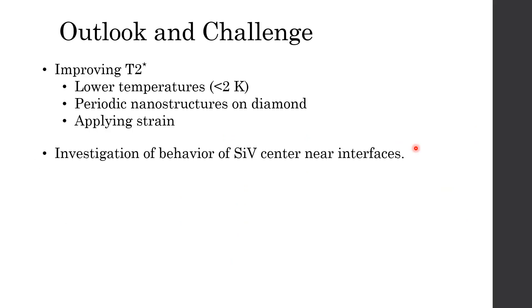Since the coherence time T2 star is limited by orbital relaxation that arises from single phonon process, for temperature below 2K, the reduced phonon occupation results in a suppression of the orbital relaxation from the lower branch of the ground state. Using the lower branch state, a qubit will then enable long-lived spin coherence.